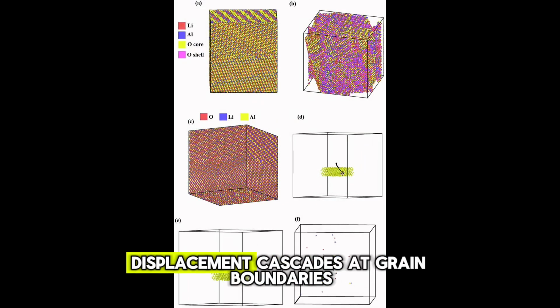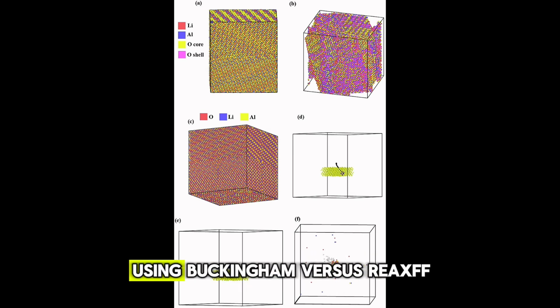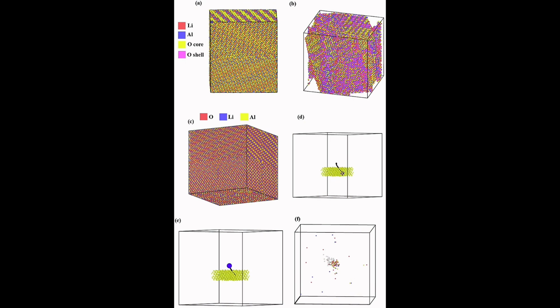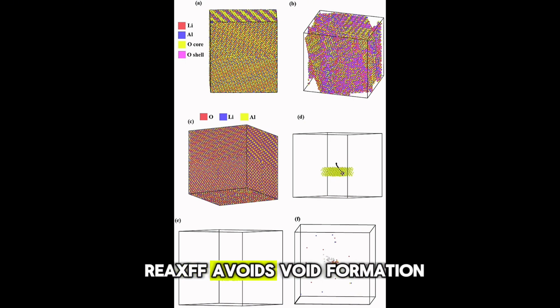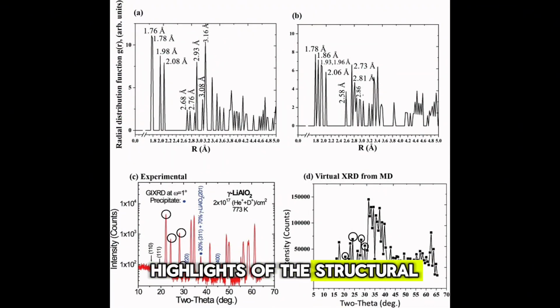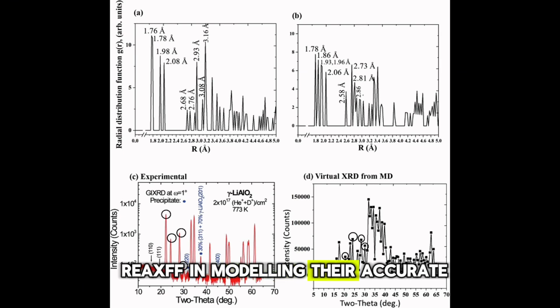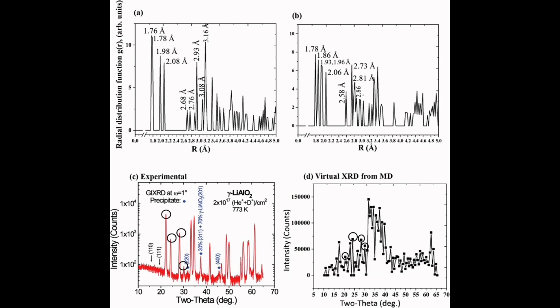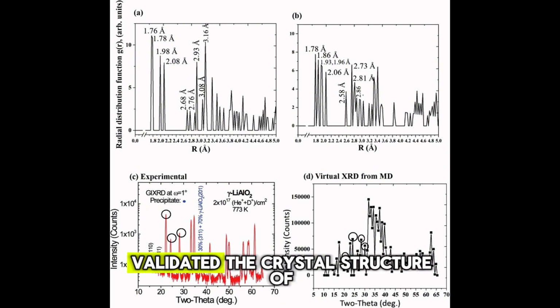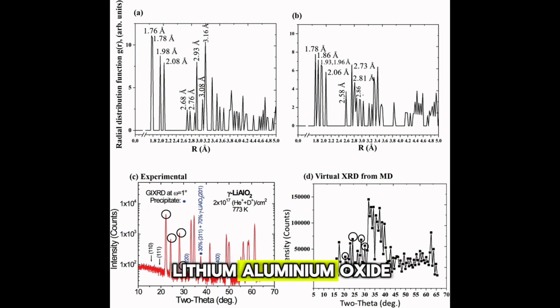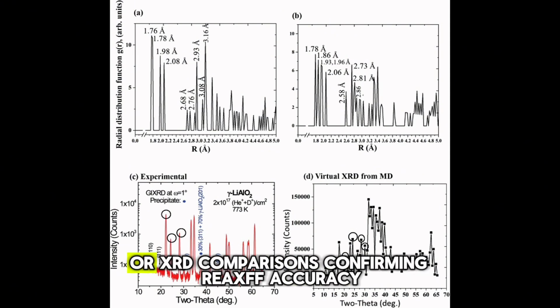This simulation shows displacement cascades at grain boundaries using Buckingham versus ReaxFF, to see how ReaxFF avoids void formation. This picture highlights the structural integrity of lithium aluminum oxide and lithium penta-aluminium octa-oxide, supporting the use of ReaxFF in modeling their accurate atomic arrangements. From this image, we validated the crystal structure of lithium aluminum oxide and lithium penta-aluminium octa-oxide using RDF comparisons, confirming ReaxFF accuracy.